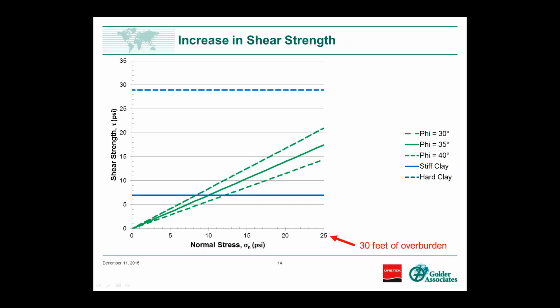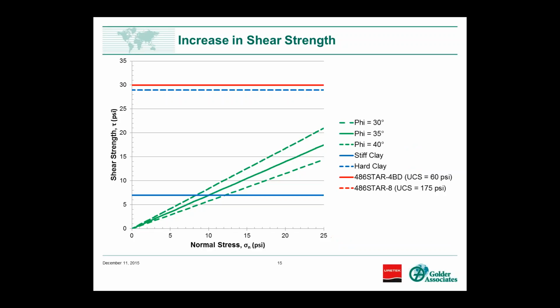So you may think, oh, the strength of this polyurethane, it's only 60 psi compressive strength. That's not very good if you're comparing it to a concrete. But you can see that red line up at the top. That's half of the compressive strength of the 4 PCF product. It's still significantly stronger than pretty much any of the soils that you're going to encounter. And I think the actual strength is probably going to be higher than that. For the other product that I'm using in this comparison, that 8 PCF, half of 175 is about 88 psi. So that's off the chart. So the first thing I wanted to point out is that this material does definitely have strength. This is not a weak material.